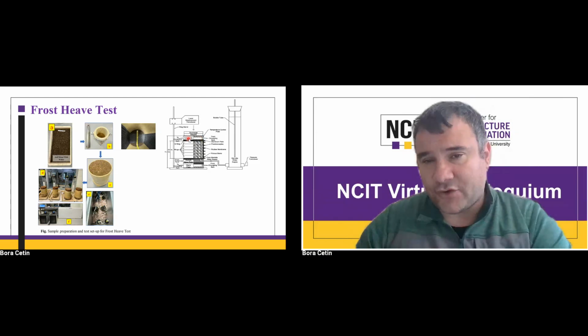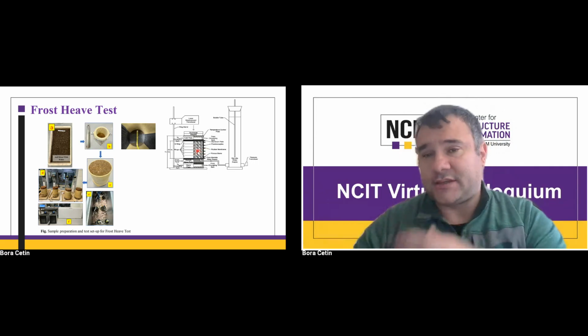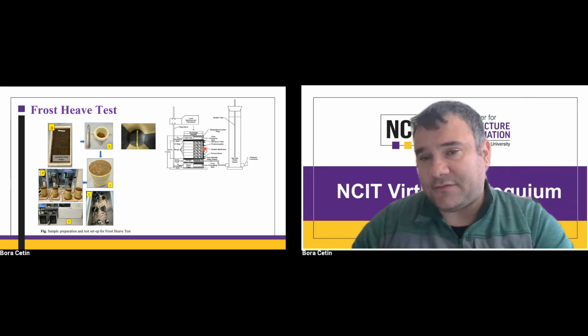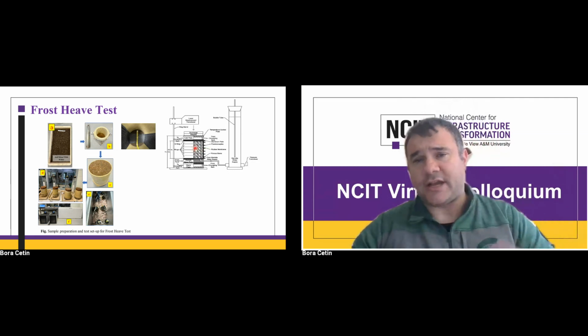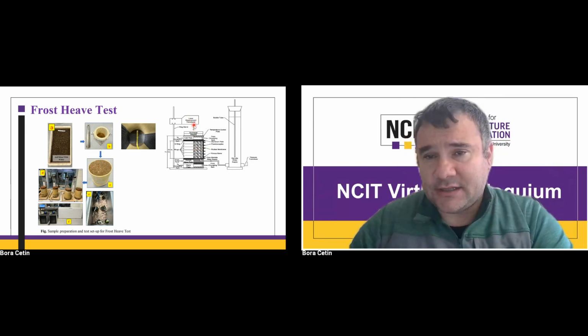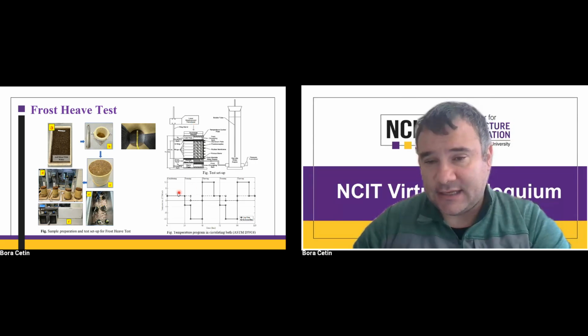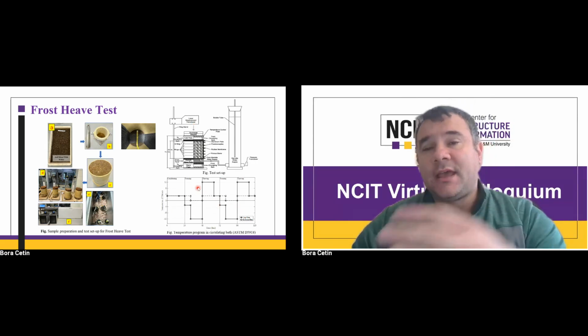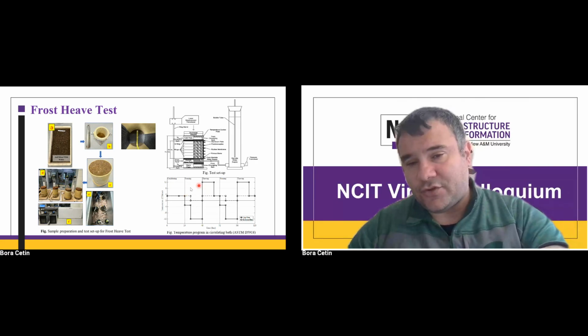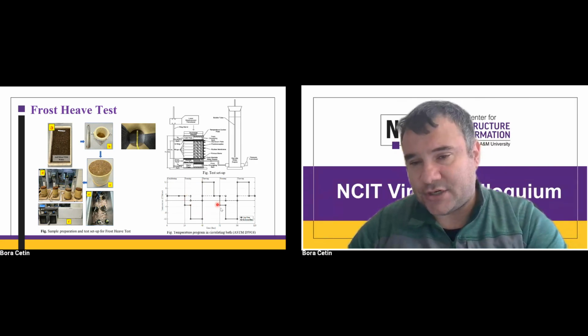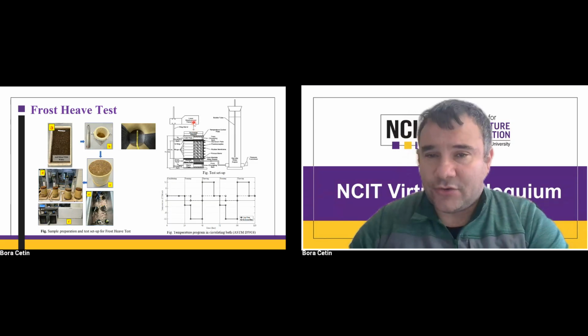And when we start freezing from the top, that's what happens in the field. We see how much water is being sucked in, and if you put the Wicking geotextile at any level, we also try to configure which level we need to put the Wicking geotextile at that would be more efficient to use. And you monitor how much the material, when you apply the freezing and thawing cycle, here is our temperature program, how much soil is heaved during this thermal gradient and temperature scheme that we apply, and how much it thaws when you warm it up from the top.